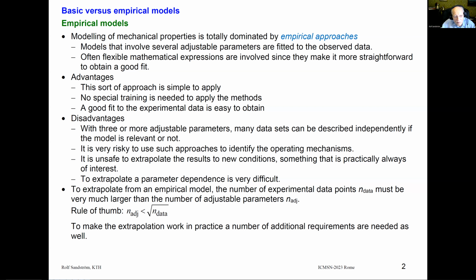It's not impossible to extrapolate from an empirical model. The basic requirement is that the number of experimental data points must be very much larger than the number of adjustable parameters. The rule of thumb is that the number of adjustable parameters should be less than the square root of the number of data points. To make the extrapolation work in practice, a number of additional requirements are needed.